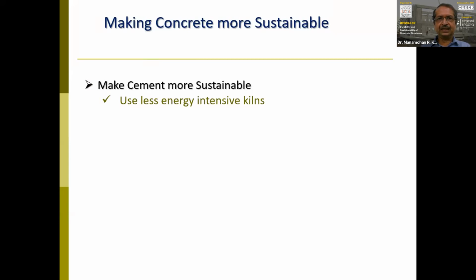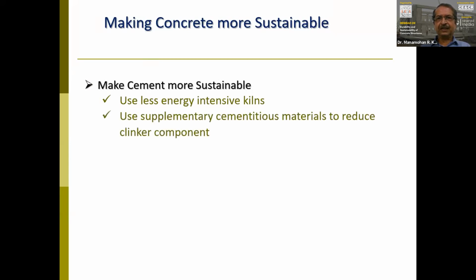It's by using less energy intensive kilns during manufacture, and using supplementary cementitious materials so that we reduce the clinker component or the OPC component, because the word that people normally use, that 1 ton of cement production produces 1 ton of carbon dioxide footprint, is basically for the production of the clinker, that is the OPC. So if we use supplementary cementitious material, we reduce the clinker content. Suppose you are using fly ash 35%, you are reducing the clinker content by 35%. And if you are using slag upwards of 50%, you will be reducing the clinker content to less than 50%. So it will be 40% or 45% or whatever that is there.